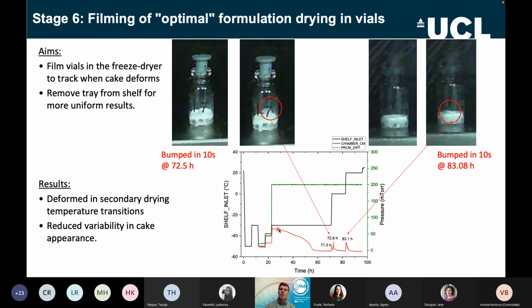So in the freeze dryer, we can measure the pressure applied, the vacuum applied essentially, the temperature it's at, but also you can track the amount of water coming out. It's got a sensor on it that determines how much water is being removed. And you can see a lot of water being removed in this primary drying phase, and then it comes to an end. And when you suddenly increase the temperature and reduce the pressure, you get these bumps in water coming off. And it's at these moments that little bubbles and cracks started to form in the cake. So it was the sharp changes into different drying phases that were causing bumping at particular points and deformation of the cake.